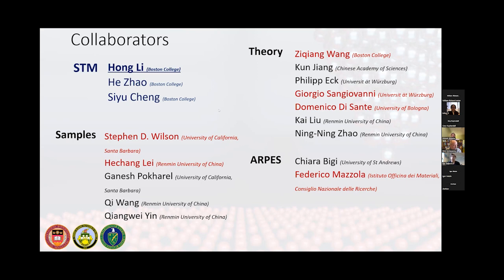The QPI is basically what allows us to have the momentum resolution, and you can think of it as like ARPES using STM. Except ARPES can give you the band structure for all the bands for most materials below the Fermi level, while STM can only do that for specific cases. We don't directly measure the electronic momentum. What we measure is scattering. An electron comes in with some momentum and scatters off a defect in another direction. These two waves interfere and give us standing wave patterns in STM. So what we see is not momentum, but momentum transfer. I glossed over that for the interest of time.